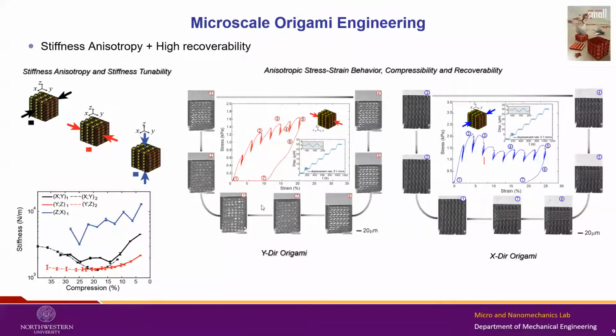As I said, we were able to recover most of the properties that come from this foldability. The first interesting properties that we were able to see were the stiffness anisotropy. Once you have this 3D Miura-Ori tube assembly, you have two directions that are foldable, and then you have one direction which is stiffer, which is the one with the zipper coupling that I mentioned before.